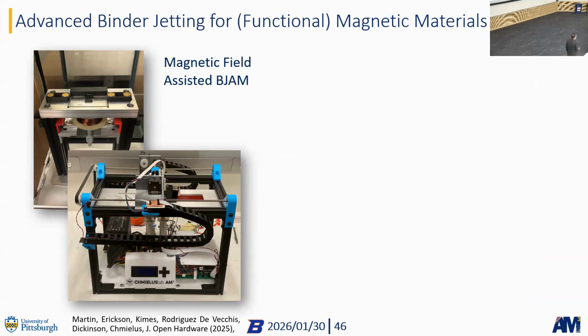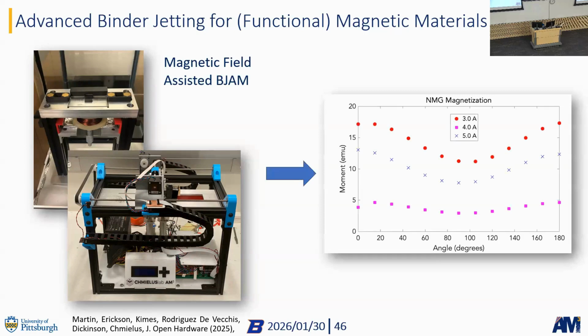What we then also worked on is, well, we want to do this a little bit better, right? So we are building our own printers, especially for this. We use magnetic field assisted binder jet additive manufacturing to actually orient our powder during printing. What we can see is, depending on the orientation of the printed structure, we actually have a maximum direction, which is the aligned direction, versus a minimum for these materials. So we can align our grains in a polycrystalline material that is printed via magnetic field assisted binder jet 3D printing.